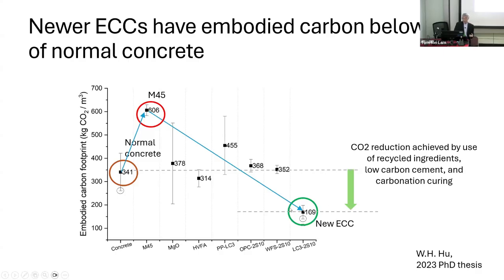In fact, this last point here was created by one of my latest students, just before I retired, now at National Taiwan University. He was able to drive down the carbon emission to below that of normal concrete. The secret is to use a very low carbon binder. Some of you may have heard of the LC3 binder, the limestone calcined clay binder popularized by Karen Scrivener in Switzerland. That was very good.